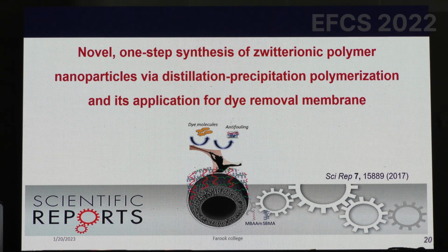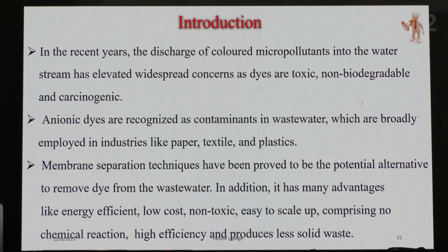What we have done here is that zwitterionic polymer nanoparticles were synthesized by the DPP method, and these were incorporated into a polymeric matrix, and then hollow fiber membranes were fabricated. These were done initially with my collaborator at UTM Malaysia, and then these membranes were used for the removal of dyes present in wastewater. For industrial wastewater that is rich in dye, I can suggest this is one such fantastic material for efficient removal; even up to about 97 to 98% of the dyes were successfully removed.